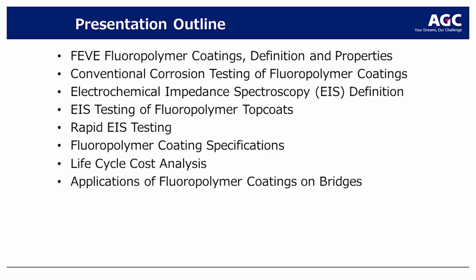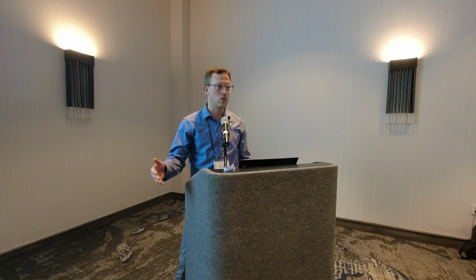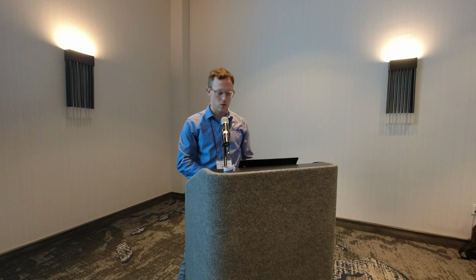So we make the fluoropolymer, the FEVE coating, and we'll talk through conventional corrosion testing, some of the weatherability that we have, and then go into some of the EIS, Electrochemical Impedance Spectroscopy, that we've looked at and we've seen within our resins for some top coat formulations that we've had, and then get into some of the life cycle cost analysis. And this is within the steel portion of when you're looking at bridges. So you use it in the conventional three-part system for when you're looking at your bridges. And then after that, we'll go through some case studies.